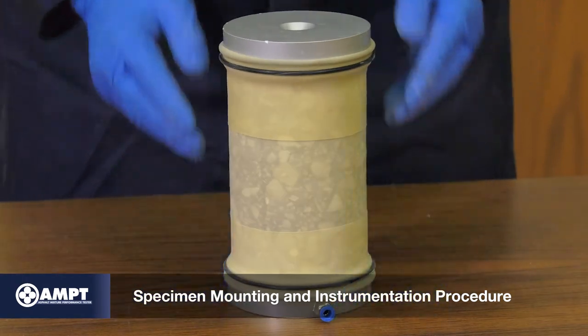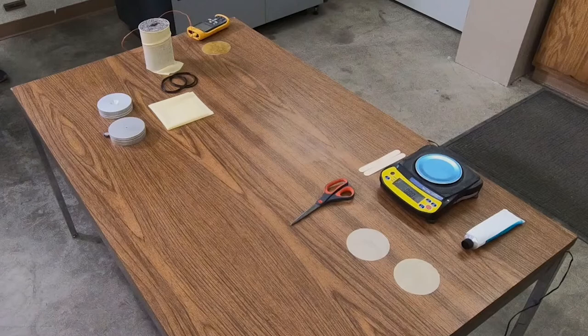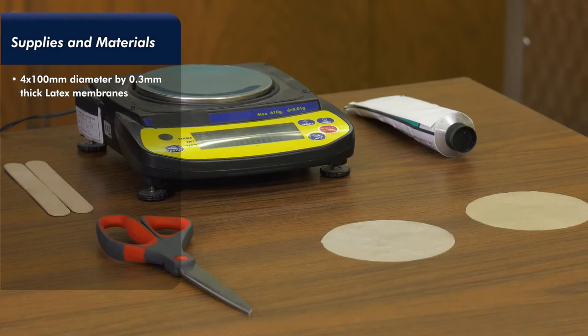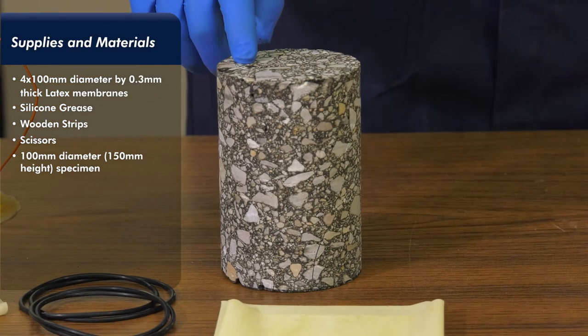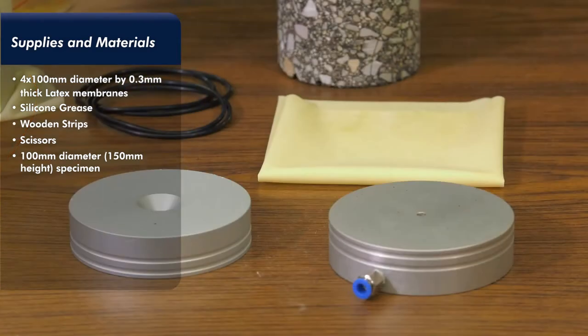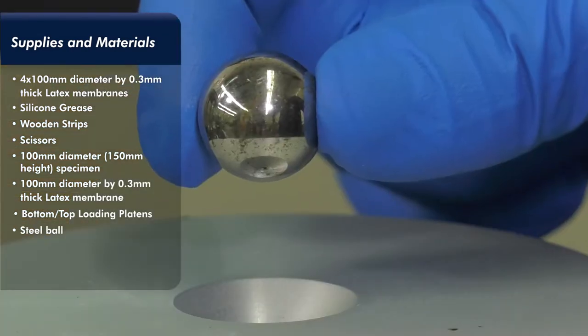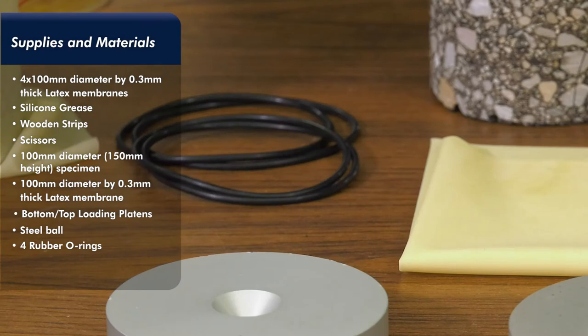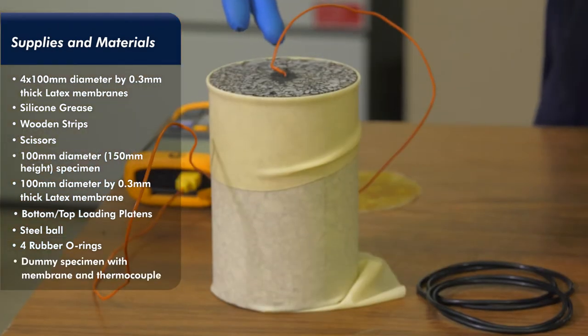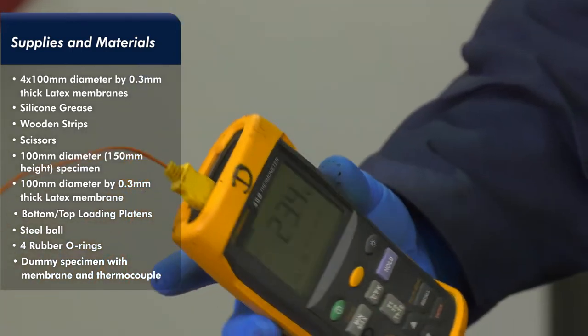Before beginning the SSR test, prepare the specimen assembly as follows. Supplies and materials are shown here and include 4 100 mm diameter by 0.3 mm thick latex membranes, silicone grease, wooden strips, scissors, 100 mm diameter by 150 mm high specimen, 100 mm diameter by 0.3 mm thick latex membrane to encase specimen, bottom and top loading platens, steel ball, 4 rubber O-rings, and a 100 mm dummy specimen with membrane and thermocouple thermal probe installed in the middle of the test specimen.